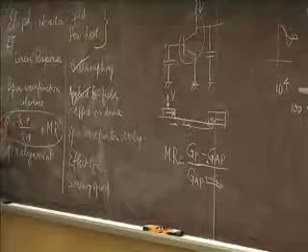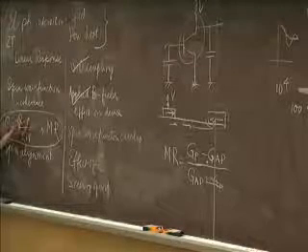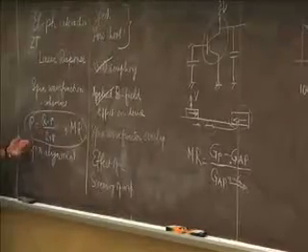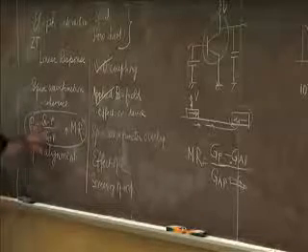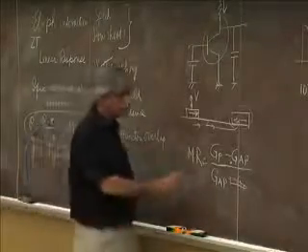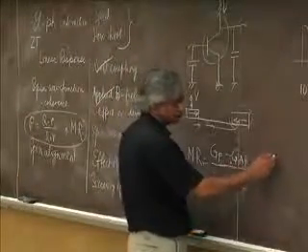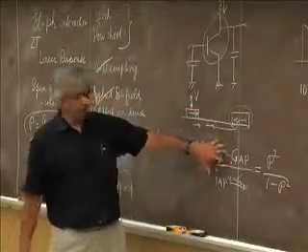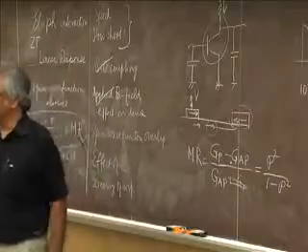And similarly, what you call polarization, again, I guess the motivation is it should be 0 when the two conductances are equal. That means you're not discriminating between two spins at all. That's what should be 0. And on the other hand, if one of them is 0, then it's like 100%. So that's how you're choosing what it is. And I think this is the standard that people use. And then the magnetoresistance comes out as P squared over 1 minus P squared. The model that I went through in the morning, I think that's what it would give you.